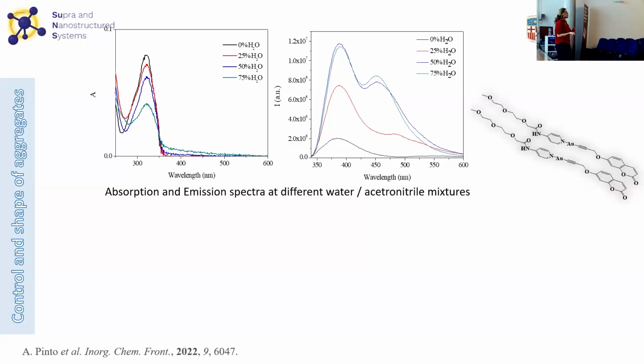So what we perform are absorption and emission spectra and observe what happens. And what we observe is that, in fact, when we increase the water content, the content of the bad solvent, the absorption band, this is the absorption of the coumarin, of this part of the molecule, is decreasing in intensity, and at the same time, the baseline is increasing. And this is directly correlated to the formation of some small aggregates.